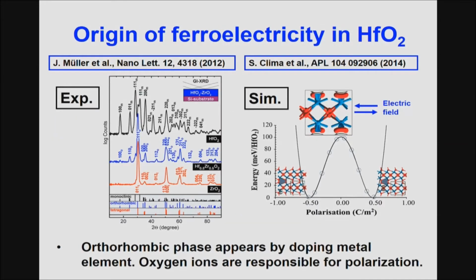Let me briefly touch on the origin of ferroelectricity in hafnium oxide, which was discovered by a German group. Of course there are several debates now, but the major consensus is that the orthorhombic phase appears by doping some element into the hafnium oxide film. Then ferroelectricity appears. Another thing is, unlike the perovskite material, oxygen anions are responsible for polarization. This is a unique feature of this material system.